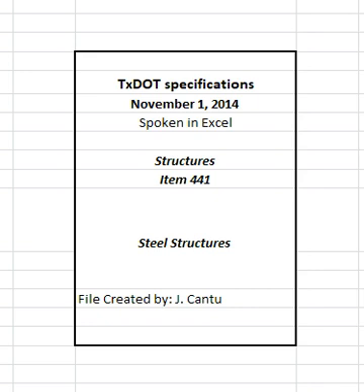3.8.2 Weathering steel. Provide an SSPC SP6 blast in the shop to all fascia surfaces of unpainted weathering steel beams. Fascia surfaces include exterior sides of outermost webs and undersides of bottom flanges of plate girders and rolled beams, all outer surfaces of tub girders and box girders, all surfaces of truss members, webs and undersides of bottom flanges of plate diaphragms, bottom surfaces of floor beams, and any other surfaces designated as fascia on the plans.